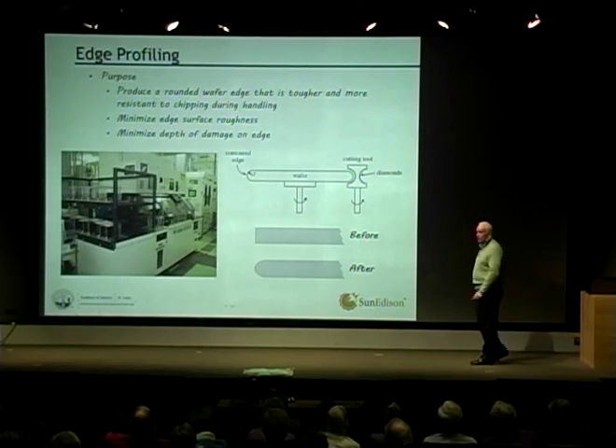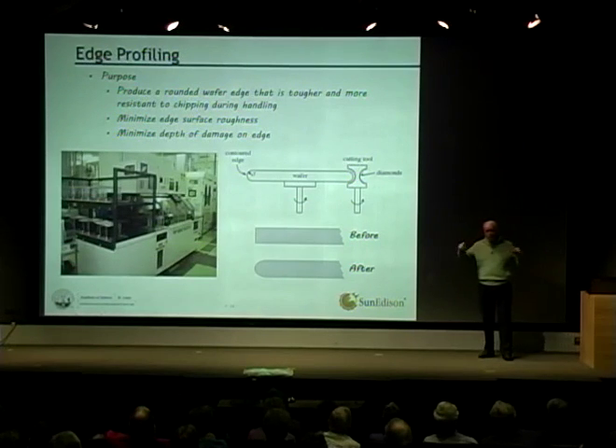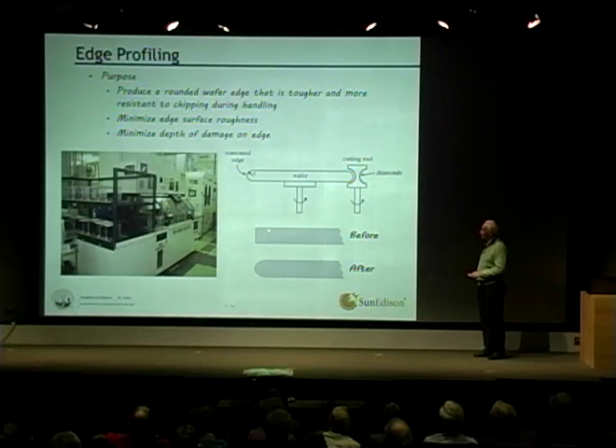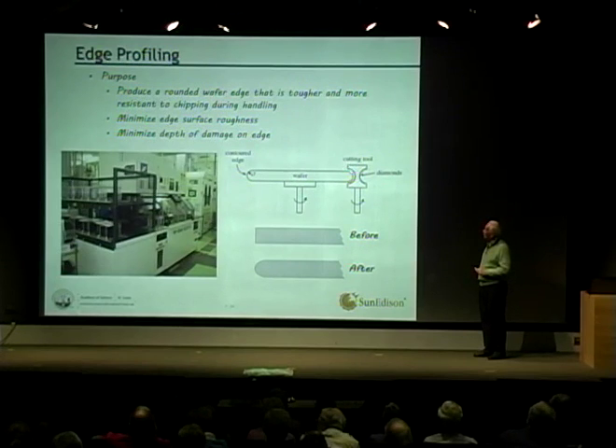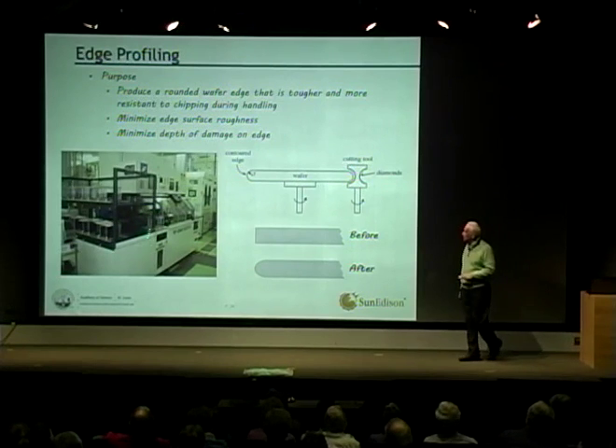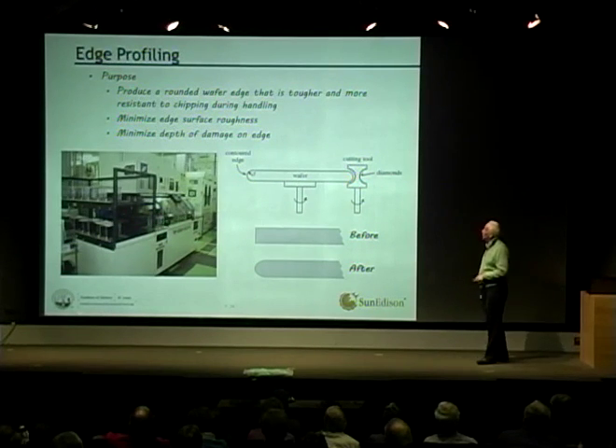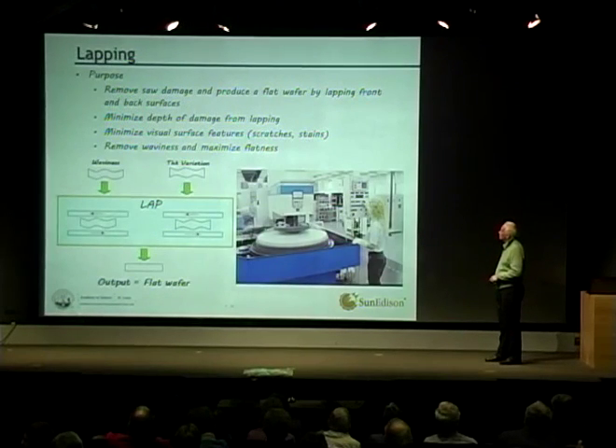So the next thing, when this thing comes off the saw, remember we've taken a perfect cylinder, we've sliced it, we now have these sharp edges, and we want to get rid of them because they can chip very easily. So we use an edge grinding wheel that is shaped like this, and the wafer that we cut spins on a spindle. We grind rounded edges, and it looks like this. Okay, and here's the machine that does it. It's fully automated, all handled with robots.